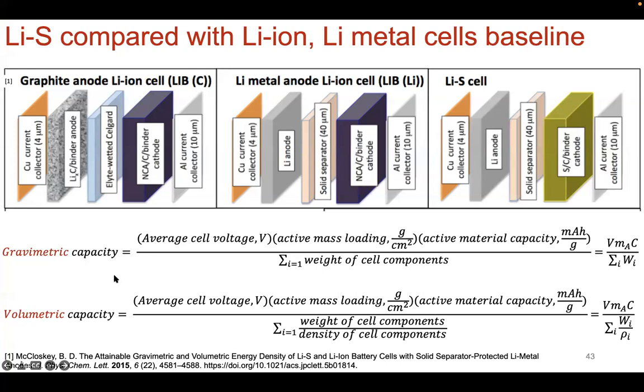Now, in terms of comparison, it's pretty straightforward in terms of calculating the gravimetric capacity and also the volumetric capacity, right? So for gravimetric capacity, you just take your average cell voltage, multiply it by the active mass loading times the active material capacity, and then, if it's gravimetric, you divide that by the mass of all the components. It is really that simple. In terms of volumetric, you divide by the density to get the volume, but it's just that. So now this takes into account all the materials, not just the active material that we've been talking about before, but the mass of the current collector, the mass of the separator, the mass of the electrolyte wetted Celgard separator, all that. So it's quite parametric, and it is a very useful study to analyze.